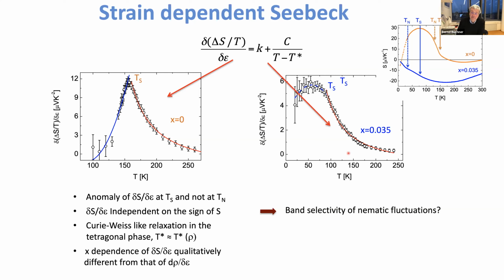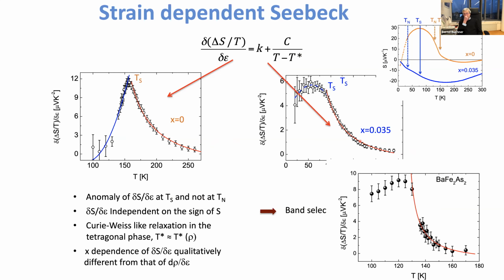Next thing is that in both cases, you can again fit these Curie-Weiss laws, and the Curie-Weiss constants which you obtain here are very similar to what you get from the resistivity. However, the doping dependence of the size of the effect is different. So the Seebeck effect here is much larger in the parent compound than it is in the doped compound. So in that sense, it's already telling you that it's not straightforward to take the same susceptibility. And it's also maybe remarkable that when you do the same experiments on BaFe2As2, it's surprisingly similar. So that seems to be rather generic, this behavior, how this detail of the Fermi surface changes as a function of strain.